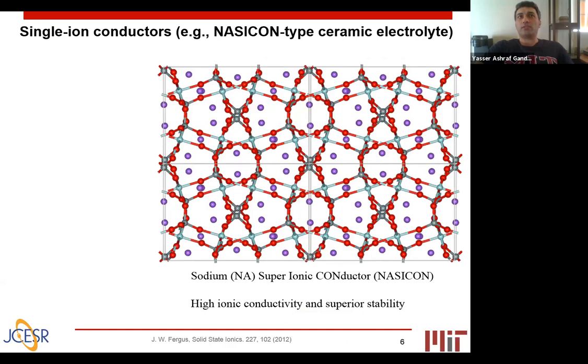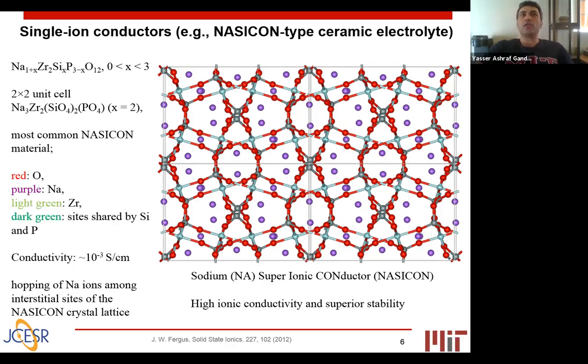NASICON-type ceramic electrolytes as single ion conductors have been used successfully for solid-state batteries. NASICON stands for sodium superionic conductor, and can have the generic form I'm showing on the top left corner of this slide. I'm also showing you the unit cell, including sodium, zirconium, silicon, oxygen, and phosphorus, where the red dots are oxygen, the purple sodium, light green zirconium, and dark green sites shared by silicon and phosphorus.